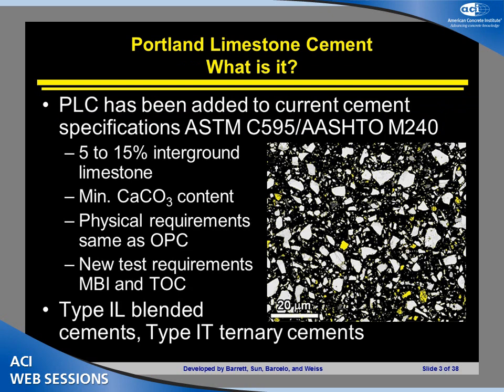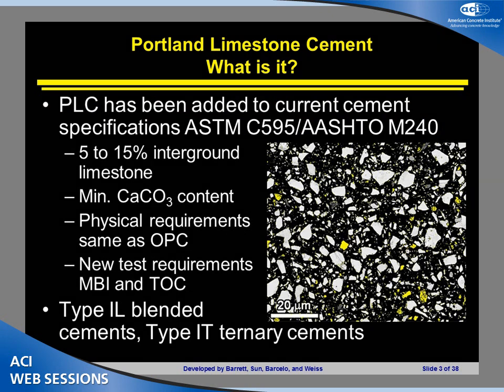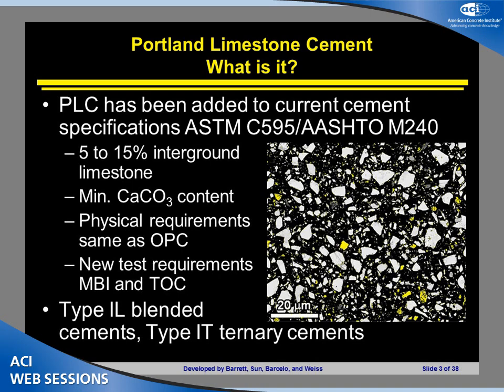As Paul mentioned, Portland-Limestone cement is now currently in the cement specifications, ASTM C595 and AASHTO M240. Here's a picture of a typical Portland-Limestone cement. When you look at it in the microscope, all the particles are not different colors like this. That's been added afterwards. But it gives you a little bit of an idea of the picture. Basically, the white particles here are our typical clinker portion of the cement, and the yellowish particles are the limestone in this case. And Paul covered quite a bit on the background, but we're looking at really 5 to 15% additions.